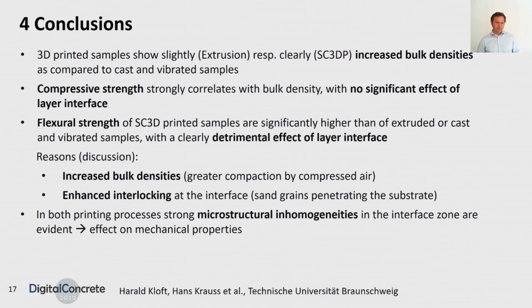And the reasons we discussed are, on the one hand, the increased bulk densities, which means lower porosity, caused by the greater compaction by compressed air, and on the other hand the enhanced interlocking at the interface caused by sand grains penetrating into the substrate. And here also the rheology of the paste phase may be of importance, how deep and how strongly those sand grains penetrate into the substrate. However, in both printing processes, we saw strong microstructural inhomogeneities in the interface zone, and they may be one of the most important reasons for a loss in performance in terms of tensile or flexural strength. And here we should put focus in future research, in my opinion. So now I hand over the word again to Harald to give you an outlook.